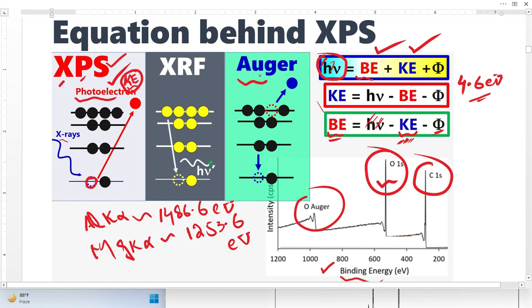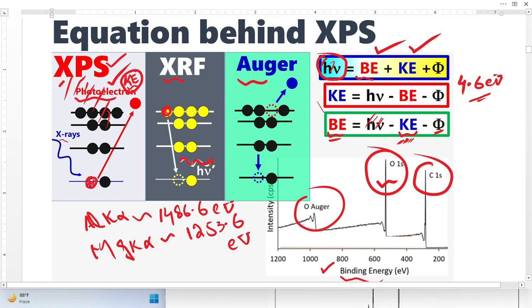The Auger process is basically not taking part in this photoelectron emission. Once there is a vacancy in the core shell, there is also an X-ray fluorescence probability — when a higher orbital electron falls to fill the vacancy, radiation is emitted in the form of X-rays due to the change in energy. But in this energy range, we do not consider this phenomenon in XPS, and XPS detects electrons, not X-rays, so it has no importance here.